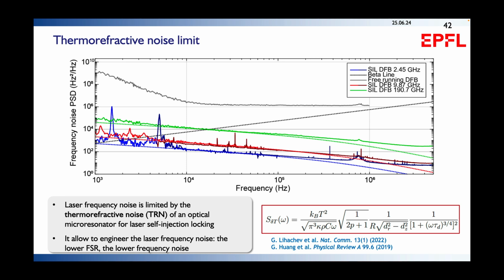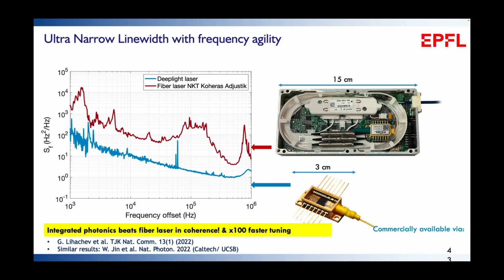So you can see here from green to red to blue, we are making longer and longer spirals and achieve a phase noise here, as I'll comment, that can even be lower than the phase noise of a fiber laser. So this is a result that surprised us when we first measured it some years ago. What's shown here is the frequency noise spectral density of a fiber laser from NKT. So it's a workhorse for fiber sensing. And what's shown here is the phase noise of one of these high Q silicon nitride endowed optical resonators that we use for self-injection locking to a DFB. What you can see here is that we can operate even below the phase noise of a fiber laser.